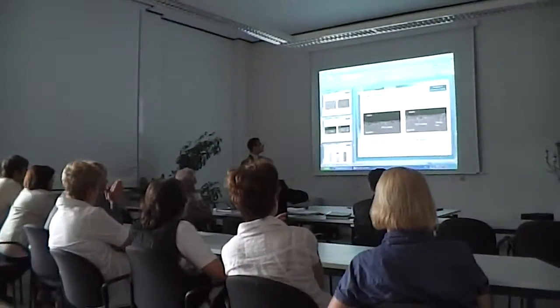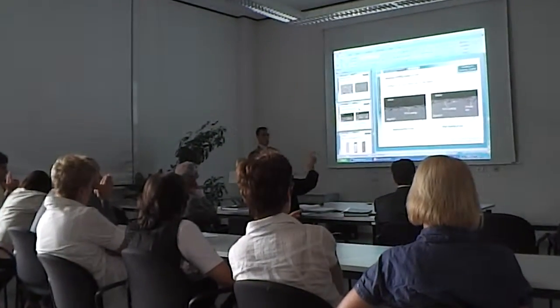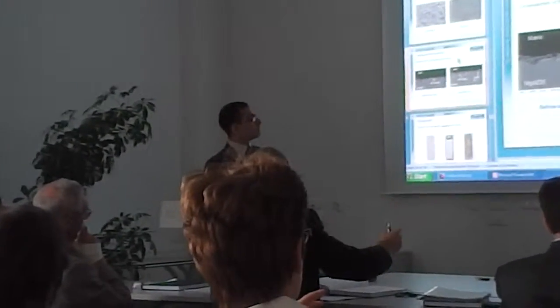So we know that once in a while the upper layer is going to be removed. Do we have any penetration of the lower layer? That would be interesting. Why was the upper layer removed? Because here a silicate film is formed over the surface of the substrate. Yes, Mr. Darvish, we know that this is the case in your specific experiment, but some people get rid of that to have a nice surface. And then the question is, is your sol able to penetrate the cracks or the imperfections which are still in the lower layer? Did you check that? No, I didn't check because I didn't remove the outer layer.